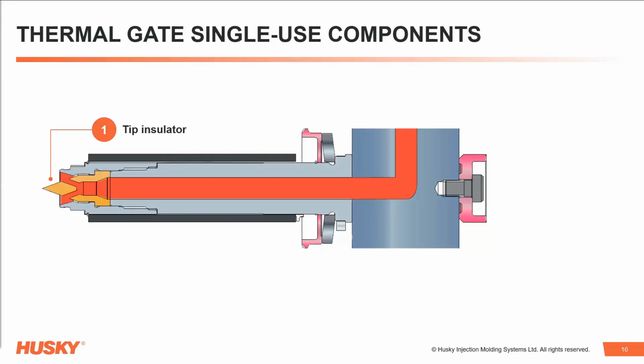Nozzle tip insulators are an item that should be replaced anytime they're removed from the hot runner, and they're easy to access by splitting the hot half from the cold half. These are used to minimize gate vestibule volume for heat-sensitive resins or to improve color change. Reusing them might cause them to crack, which can create stagnation areas and streaking. Disc springs are another single-use component that should be replaced if removed. These directly influence the preloads that prevent resin leaks.